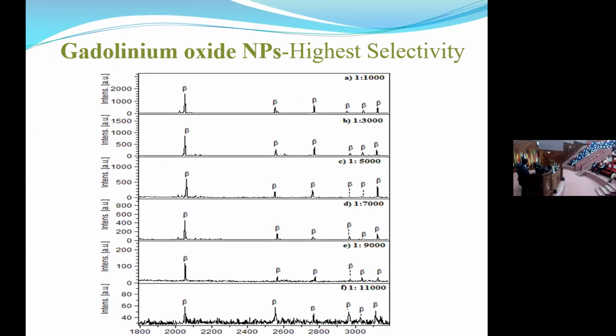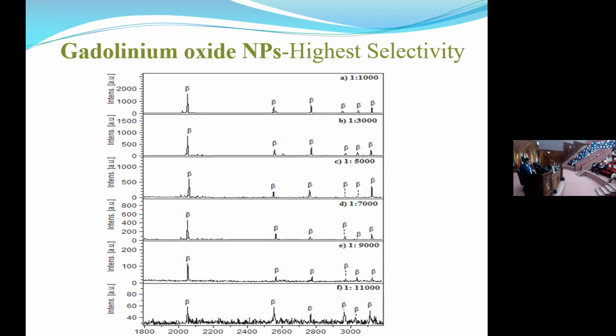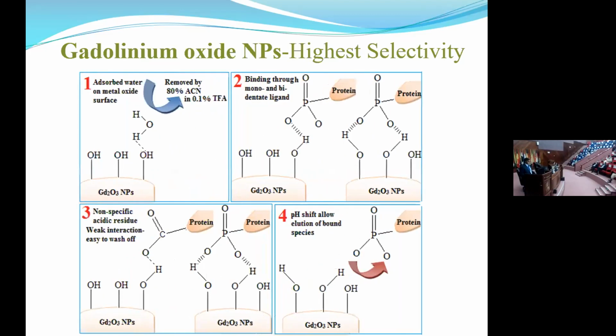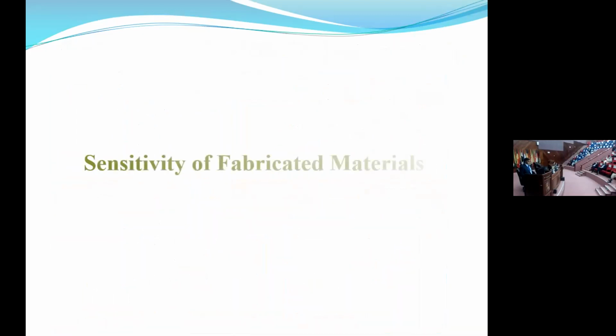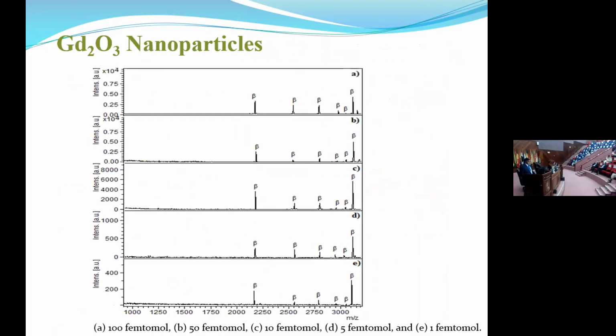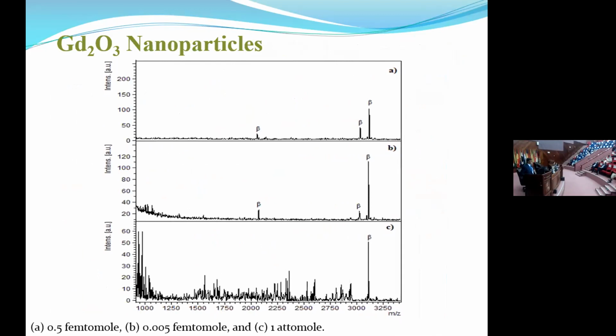You can see here, this is a beta casein. Out of that, phosphopeptides has been enriched, and the ratio made is 1 to 11,000. This is the chemistry of gadolinium oxide, how it works, and then the sensitivity of the attomole. Again, gadolinium oxide worked till the range of 1 attomole. 1 attomole means if your targeted analyte is present in this concentration, your method, the optimized method, it is not only the bead, your sample preparation conditions as well, they will enable to enrich to the level of 1 attomole.